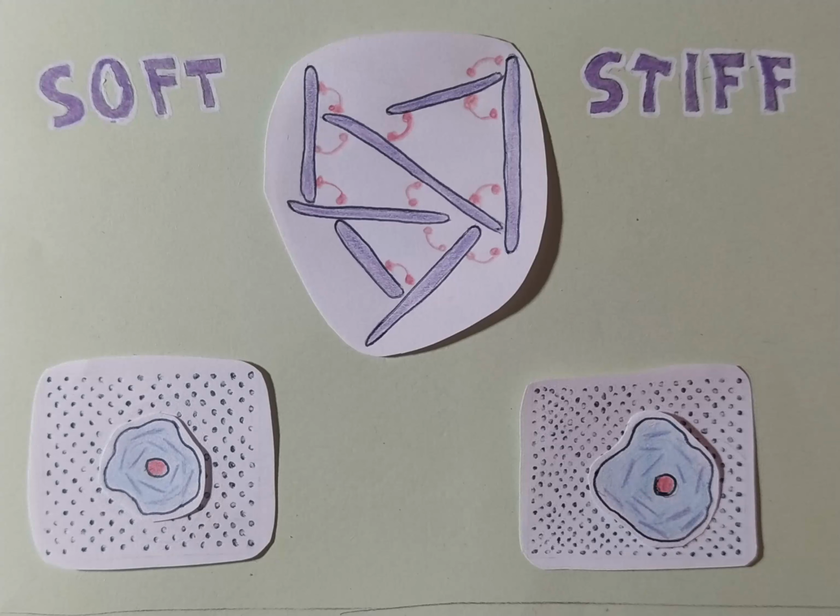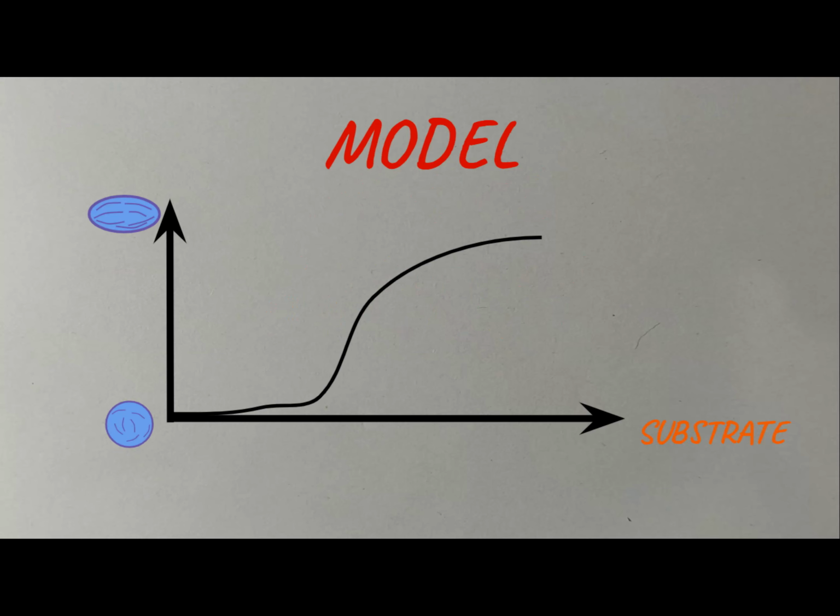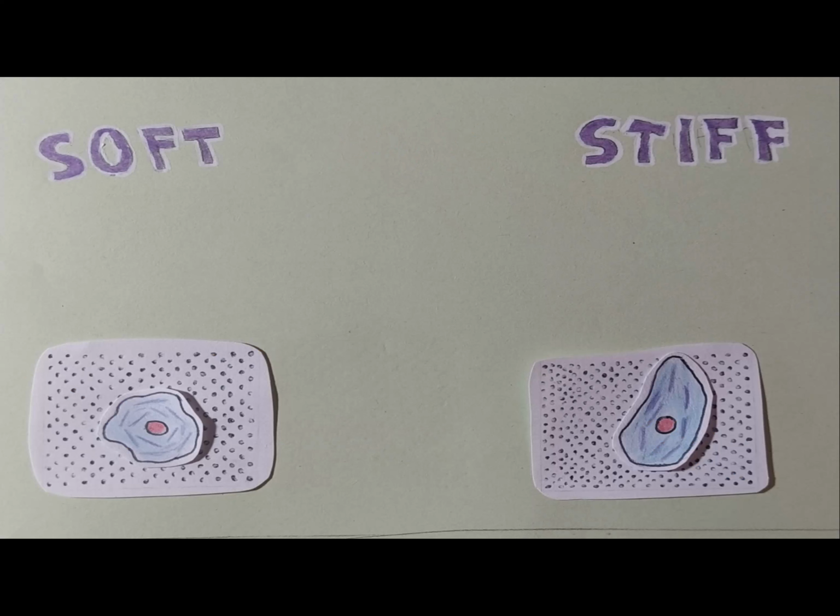Since crosslinkers increase the stiffness of the cell, we deduced that polarization was linked to the stiffness of the cell. So we derived a model, and we found that the polarization was actually a function of substrate stiffness over cell stiffness. More specifically, if the stiffness of the cell was too high compared to that of the substrate, cells would be round. Hence, knowing the stiffness of the cell, we could design material with appropriate stiffness to shape the cell round or polarized.